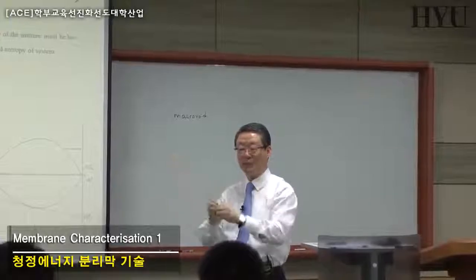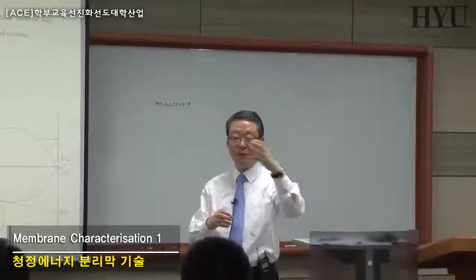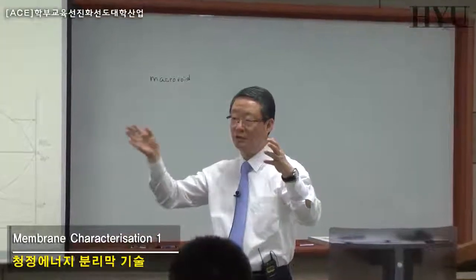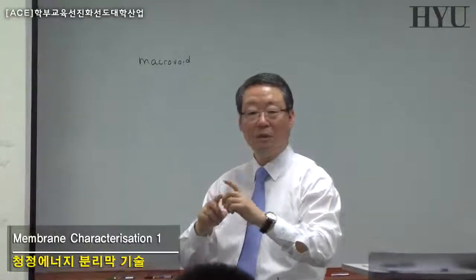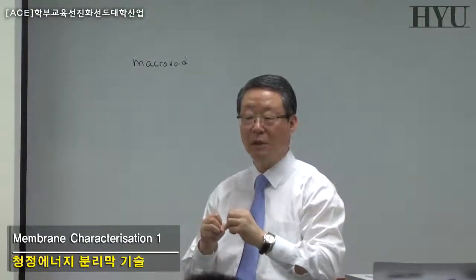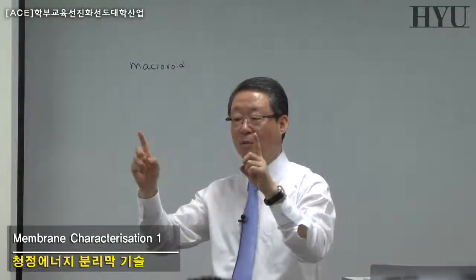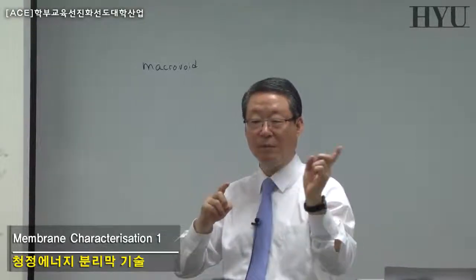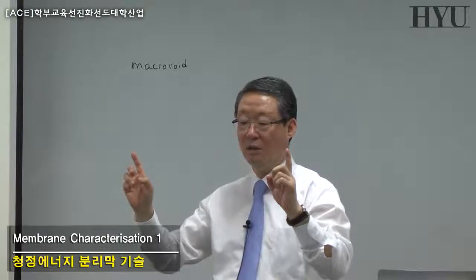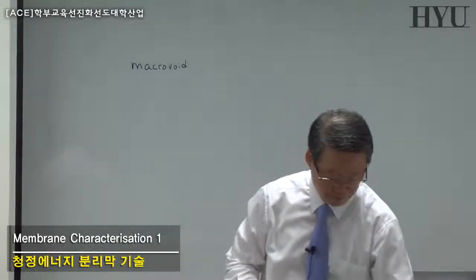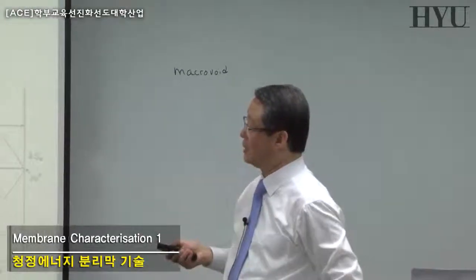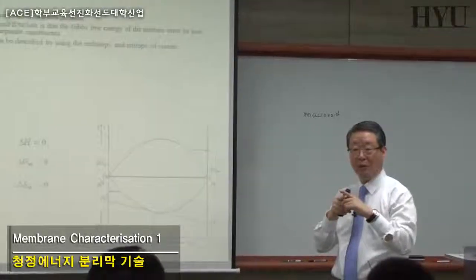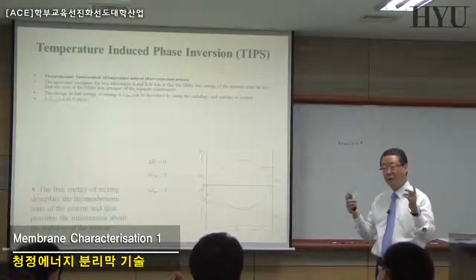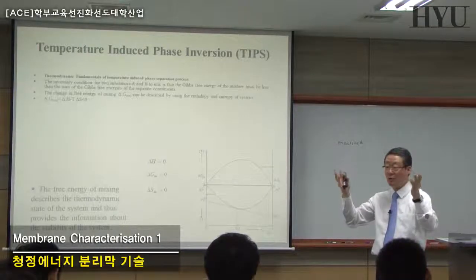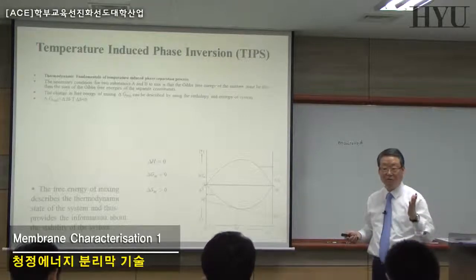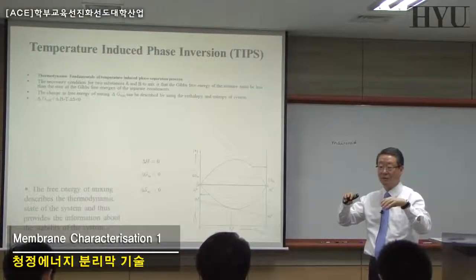the polymer and solvent to be mixed well, we have a polymer-polymer interaction, solvent-solvent interaction, and polymer-solvent interactions. When we think about our polymer solution stages in the liquid phase, polymer-solvent interaction is much larger than polymer-polymer interaction and solvent-solvent interactions, right? In that case, if polymer-solvent interaction is larger, then delta H should be negative. Right? If delta H is positive, then PP and SS interaction is much larger. Right? So that's the meaning of enthalpy changes between your polymer and the solvents.